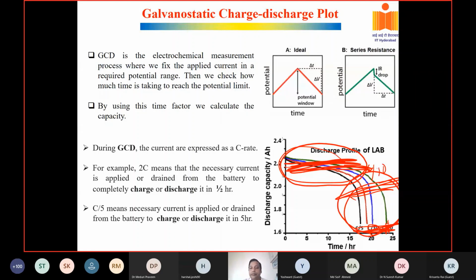So this charge discharge profile will also help you measure the capacity, since I into T gives you the capacity. And from the CV you can know what the cutoff voltages are. Here also we can determine the cutoff voltages. You don't actually have to go beyond this voltage, because you don't get any capacity. But in the laboratory we try to get more capacity.